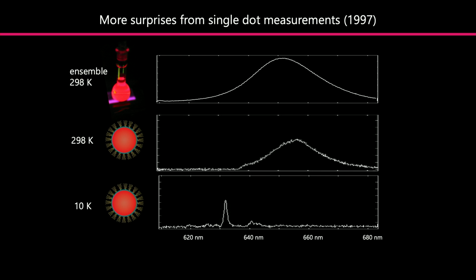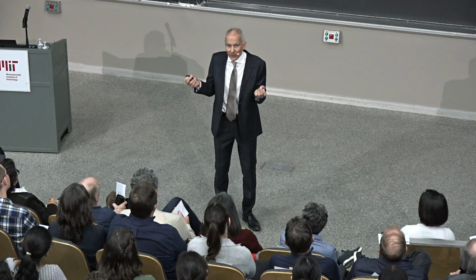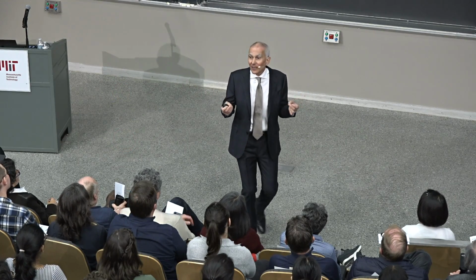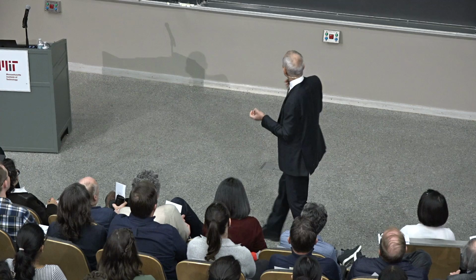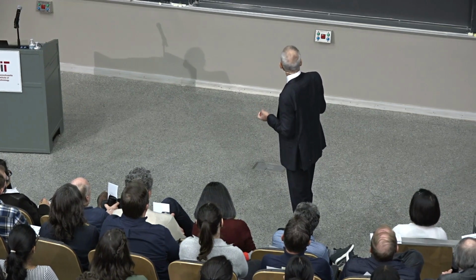So these are movies. This is the ensemble fluorescence. Okay, it's completely stable because there's a gazillion particles emitting at the same time. If you look at room temperature, you see that it flickers, it does all sorts of things. At low temperature, it's narrower, but it also moves around. These are little sensors of the environment. Okay, so you can make lemonade out of these lemons and use them as sensors of the environment, and you can learn some physics out of this dynamic spectrum.